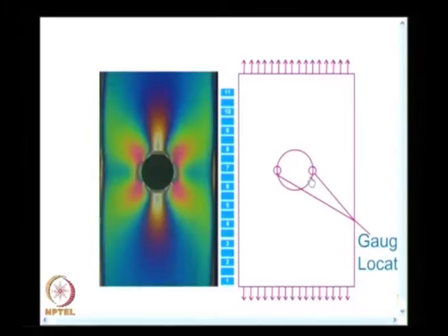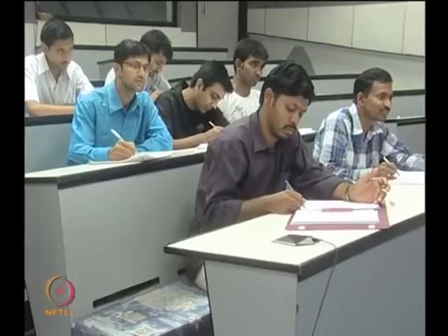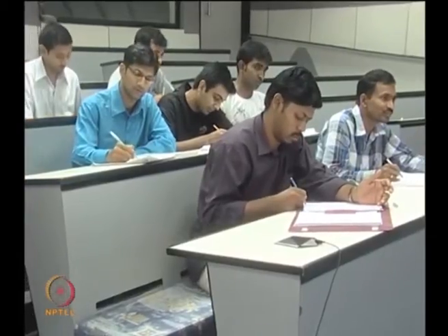All these are difficult propositions. If the hole is very small, what will you do? So, you appreciate how difficult it is to apply a point by point technique in stress concentration zones. I had also mentioned that the rudder of Concorde was failing, they used a strain gauge. They found that the strain gauge was measuring strains lower than what is actual, and a photoelastic coating test revealed that maximum strain was at a slight distance away, and they had corrected it.